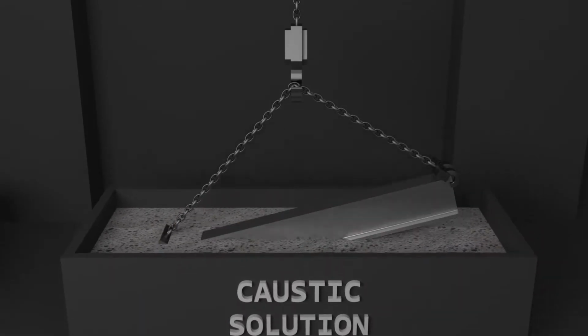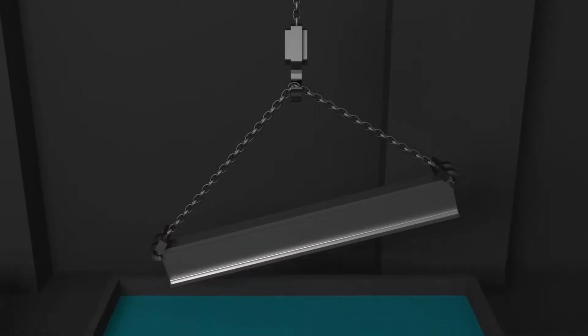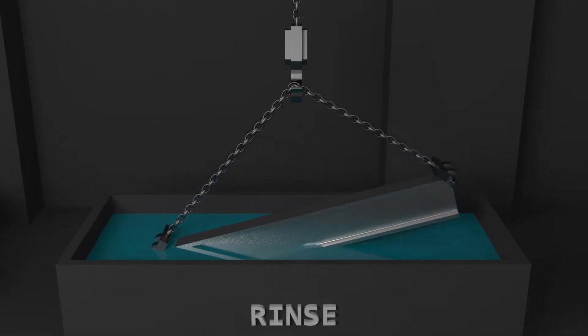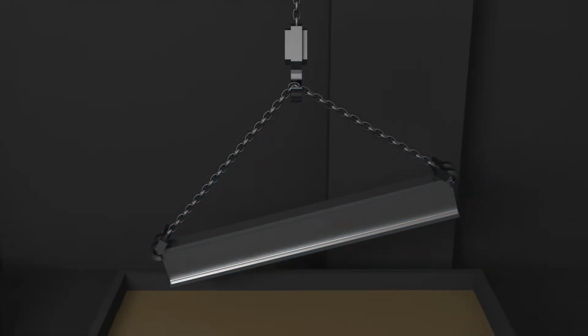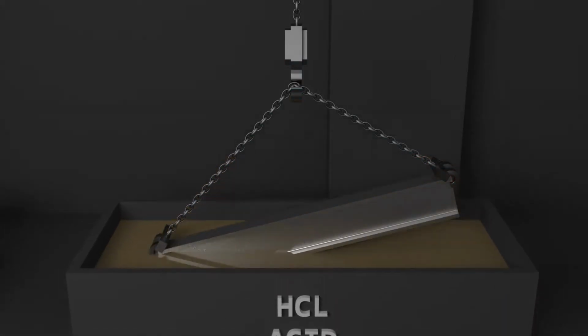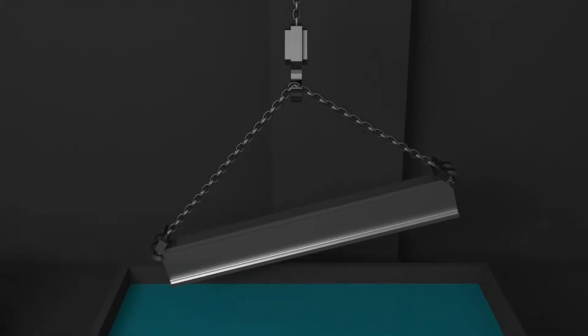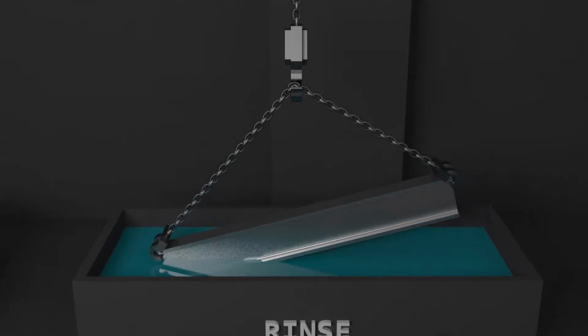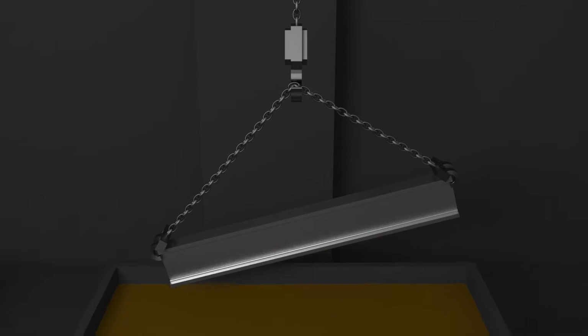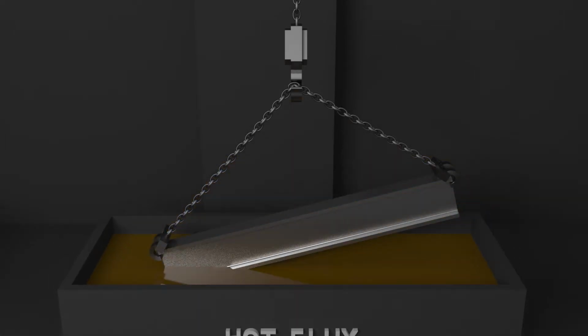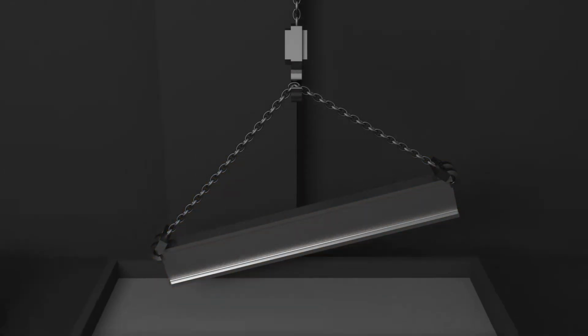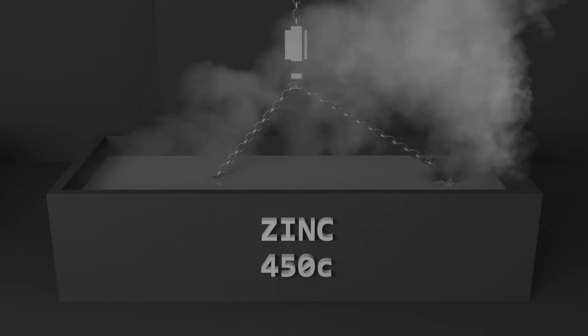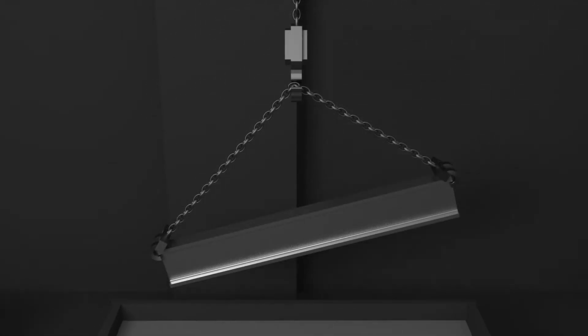Steel or iron articles are thoroughly cleaned by immersion in a caustic solution, followed by a rinse and then an acid wash. A flux is applied to the clean steel and after drying is immersed in a bath of molten zinc. A metallurgical reaction occurs, causing the formation of a coating of zinc and zinc iron alloys.